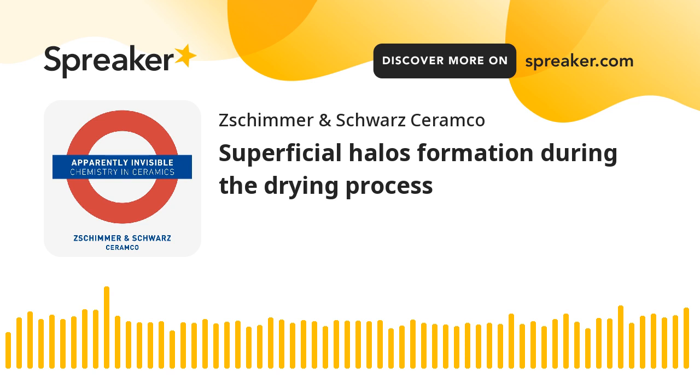As we have already said, the gradual warming inside the dryers leads to the migration of the water molecules that leave the ceramic body by evaporation. This process, however, in some cases can be not completely homogeneous over the entire surface of the tile. What do I mean? I mean that the parts of the ceramic body that rest on the roller stands may be marked by a different evaporation time and modes, we could add, with respect to those areas of the tile that do not touch the metal parts of the dryer.